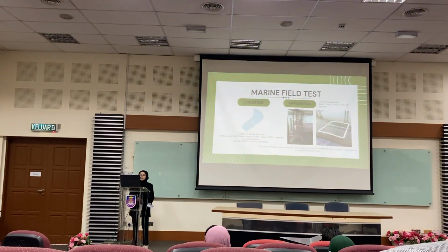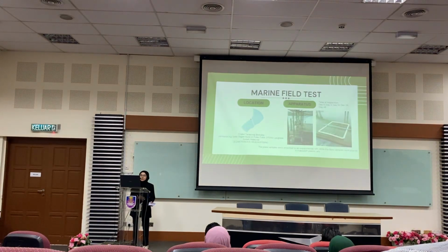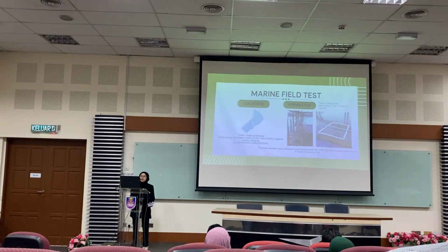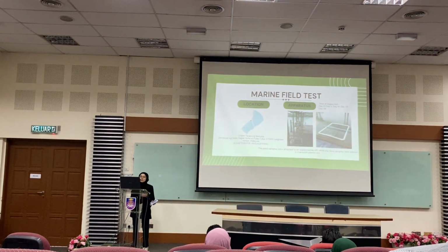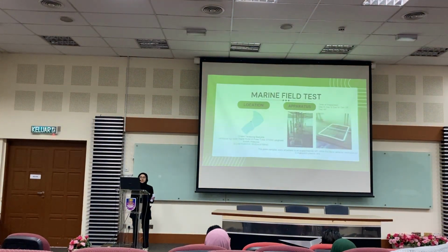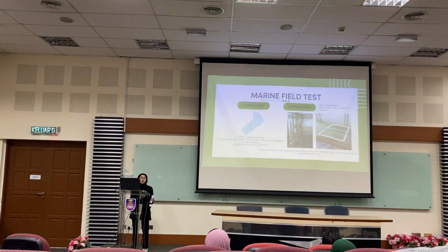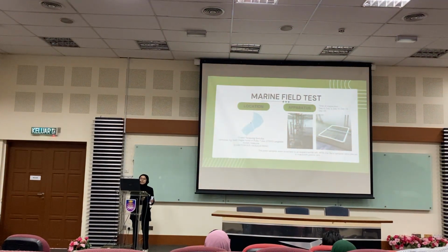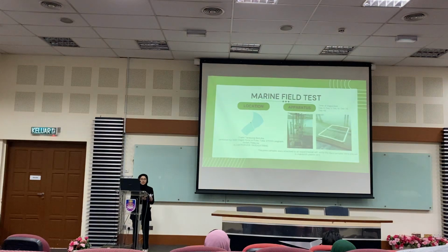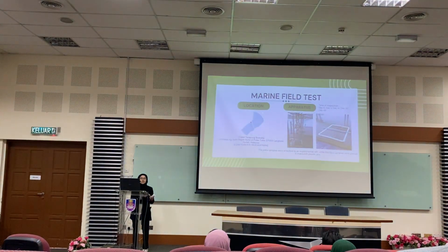The location of the marine field test was at Chalet Terapung, Tuba. The plates were secured onto the side of the experimental raft, while the fiber samples were placed in makeshift jars that had punctured holes, so there was free flow of seawater. The time of observation was on day 0, day 3, day 14, day 28, and day 49.